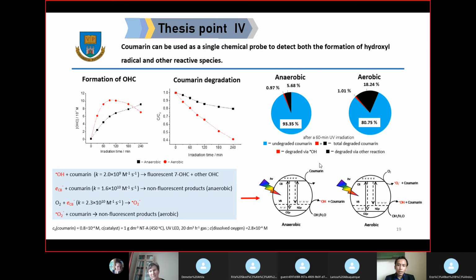Under anaerobic conditions, in the absence of oxygen, coumarin reacts directly with the photogenerated electron. However, in the presence of oxygen, coumarin can react directly with the electron, or it can react with the superoxide anion radical. But the reaction rate of oxygen with the electron is higher compared with the coumarin reaction with the electron. It means that in the aerobic condition, coumarin reacts with the superoxide anion radical rather than with the electron.